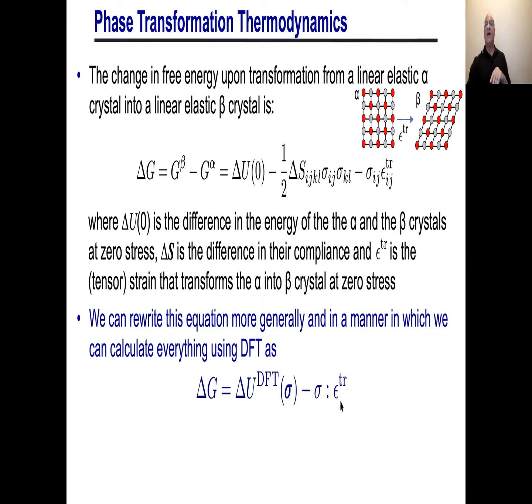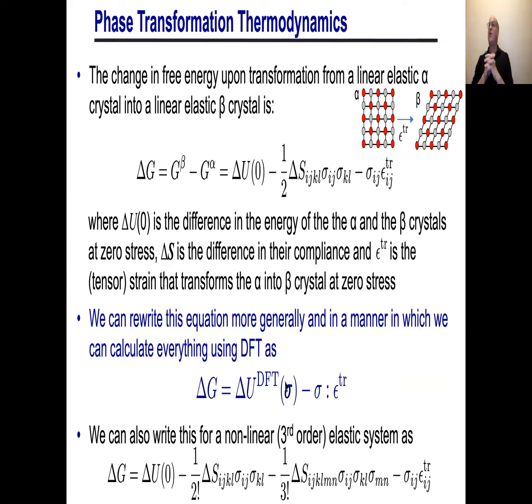Okay, and then there's the transformation part here. Okay, so this part here, that we do with DFT. An alternative is you can just take this free energy and expand it to higher and higher order in the elasticity. So if I want to do nonlinear elasticity, here I've written it up to third order in the elasticity. And as I'll show you, this third order elasticity actually does a pretty nice job for the problem that we're going to be talking about today. But let's wait until I show you some data to convince you.